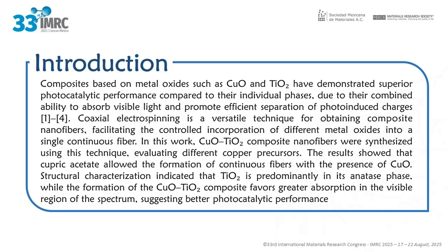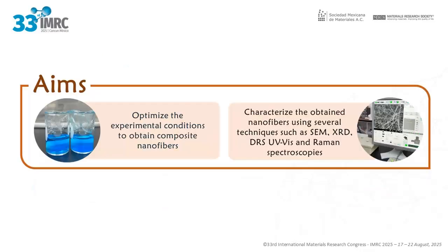In this work, composite nanofibers of copper and titanium oxides were synthesized using this technique, evaluating different copper precursors. The main objectives were to optimize experimental conditions to obtain composite nanofibers of copper and titanium oxides, and to characterize the fibers structurally, morphologically, and optically using scanning electron microscopy, X-ray diffraction, Raman spectroscopy, and UV-Vis diffuse reflectance.